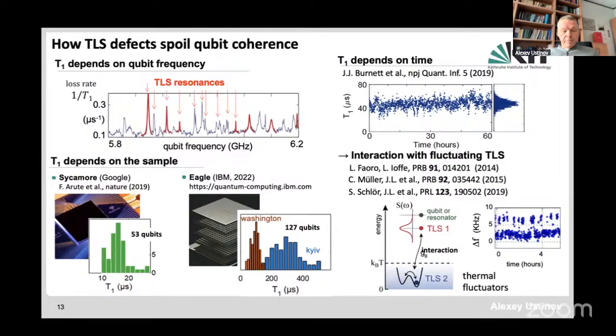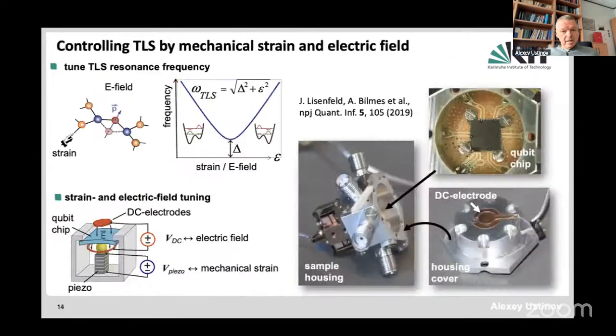So going back to studying these defects, what we proposed initially around 2012, and this was our first paper when we observed the very individual TLS, a Science paper in 2012, was to apply strain to our device. We take our chip, which you see here at the bottom left, the chip containing a quantum circuit, and then we use a piezo actuator to deform the chip, so to apply some tension between the clamps. And then we introduce some little bending of this silicon chip.